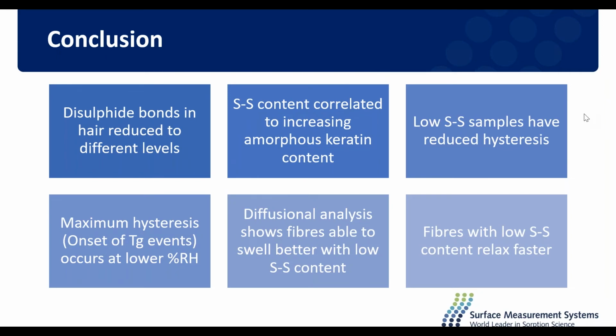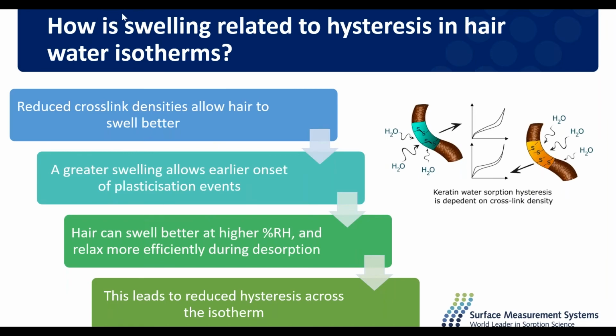So how is that linked to our original question? Is swelling the cause of hysteresis in hair? Well, reduced crosslink densities allow hair to swell better. And a greater swelling allows an earlier onset of plasticisation events and glass transition events. We've shown with diffusional analysis that hair can swell better at higher relative humidities, and they can relax more efficiently during desorption. And this is what we propose leads to a reduced hysteresis across the isotherm.